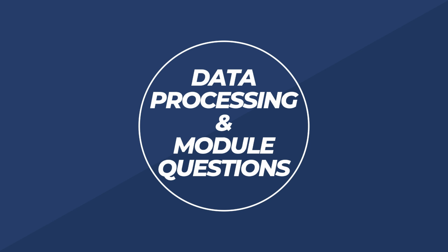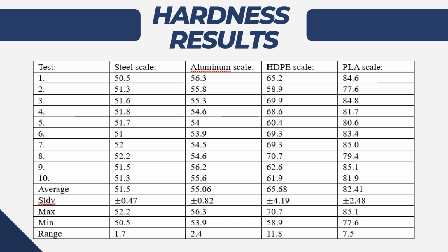Okay, we're moving on to the part where I'm going to be discussing the data processing of the hardness test and answering the module questions. As can be seen here, there are 4 materials or specimens that are going to be tested for hardness. For steel and aluminum specimens, we're going to be conducting a hardness test using the Rockwell test. For steel, we are going to use the HRA scale, and therefore we get an average hardness number of 51.5 with a standard deviation of plus minus 0.47. Whereas for aluminum, we are using the HRB scale, and we get an average hardness number of 55.06 with a standard deviation of plus minus 0.82.